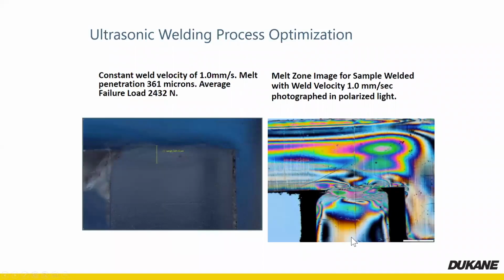So this was some parts that we welded with a 1 millimeter per second constant velocity, and it's showing the penetration. This is the heat affected zone, 361 microns of heat affected zone on either side of this assembly. And we did some pull testing on it. We got a 2,432 Newton break force. So that's where the joint broke. Under polarized light, you can see that heat affected zone is relatively small.